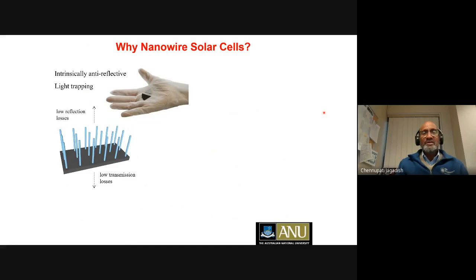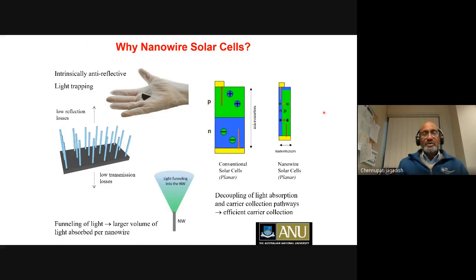So now let me move towards nanowire solar cells. As all of us studied about solar cells, we need to have a p-n junction, and you need a thick enough material to absorb all the light. You shine light and generate photocarriers, and these carriers need to migrate long distances from the top and the bottom, and you lose some of the carriers. For example, if the solar cell is about 20% efficient, then 80% of the carriers have been lost to defects, impurities or surfaces.